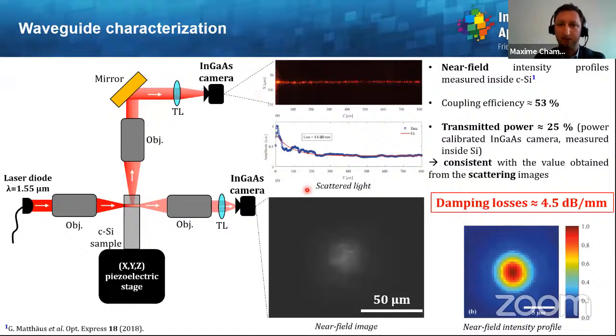So here is typically what you see with the scattered light. So the damping losses can be estimated with this. And with the InGaAs microscope working in transmission, you can see the mode field and near field images. So what we concluded on those measurements is that we had some coupling efficiency of around 53%, a transmitted power of around 25%, which is consistent with the value we obtain from the scattering images.